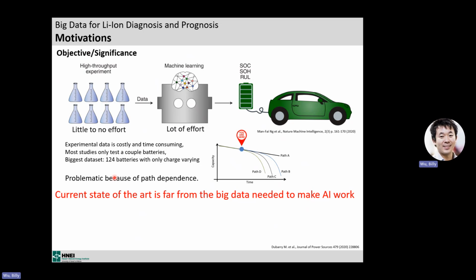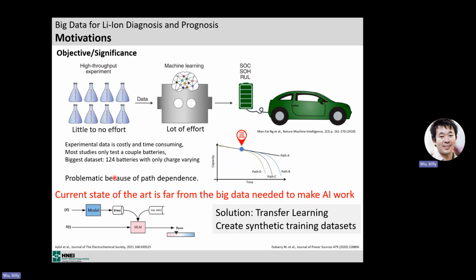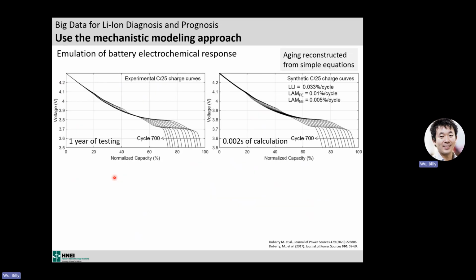So we believed at the time when we started working on this in 2017 that there was a need for more data, and maybe creating synthetic data was the solution. Add more data to the experimental one. And I just told you that with our model, we can simulate any possible degradation. So I can just take that sentence by the letter and simulate any possible combination of the parameters. And the benefit of that is versus an experiment. An example here is a test we did for a year, at the C/25 rate. Once we diagnosed it, in that case it was linear, with a bit of loss of lithium and a little bit of loss of active material, we have data that's pretty much indistinguishable. That took a year. This took less than 2 milliseconds.